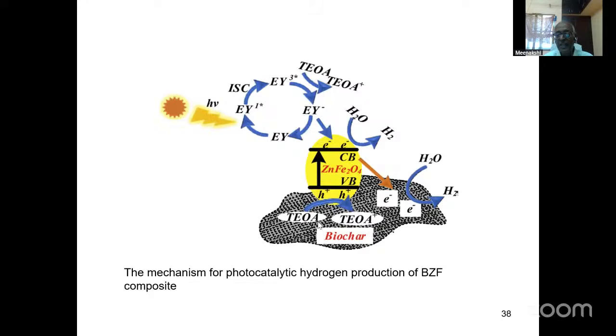So the mechanism is shown here. Actually here, what happens is the biochar abstracts the electron, just like electron abstraction, and gives it to oxygen and other things. And there is another compound called TEOA, triethanolamine. Actually, it abstracts a hole. So this is a sacrificial reagent. It abstracts a hole and also gets oxidized, because as far as the hydrogen production reaction is concerned, the only requirement is an electron, not the hole. The hole will affect the hydrogen evolution reaction, so the hole should be captured and removed. To capture and remove the hole, the sacrificial agent TEOA is used, and that removes the hole so that the electron is freely available for the production of hydrogen.